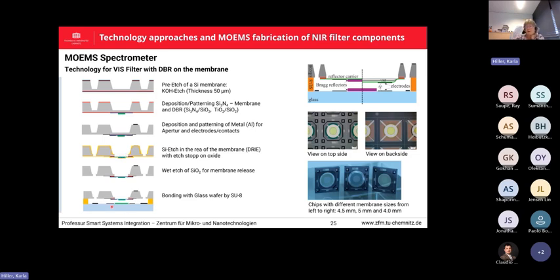For the lower wafer, as already mentioned, we have a patterned glass wafer where we have the electrodes and also the layer stack, same layer stack as on the membrane. And to get the optical distance between the two wafers, we used SU8. This is an epoxy which can be patterned by lithography. So we can adjust the thickness by the spin-on, choosing the right material, and the spin-on process needs to be very precise. And then this also serves as a bonding layer between the two wafers.